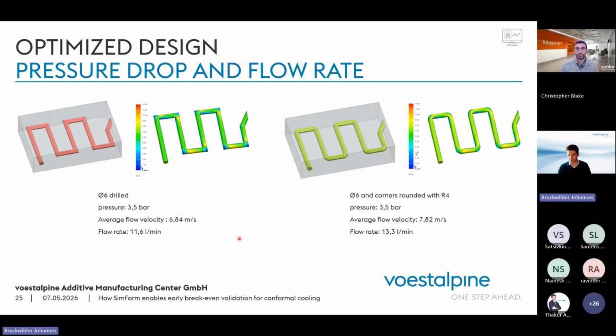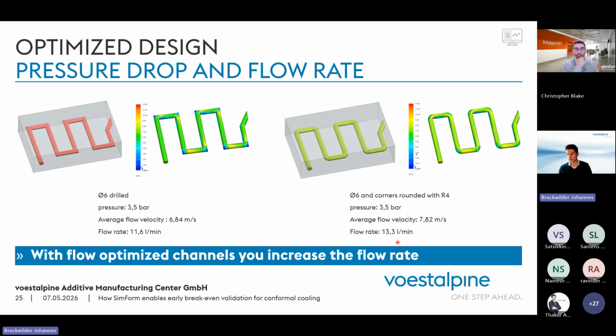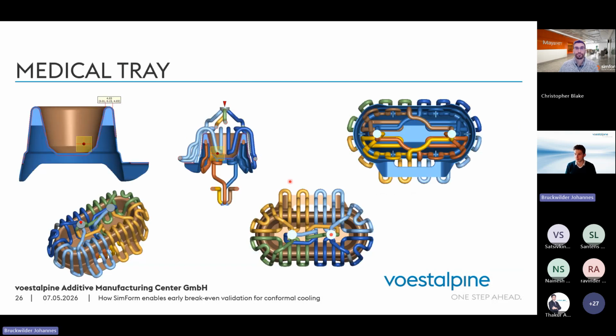It's important how you apply the conformal cooling. Another very basic example, here you see some drilled channels, diameter of 6, and you get a flow rate of 11.6 liters per minute. By just rounding those corners, you increase the flow rate up to 13.3 liters. So with conformal cooling, we always have those flow optimized channels. And as you see it here, this is a drilled channel version. The flow rate optimized version can even be more complex. And how complex can it be?